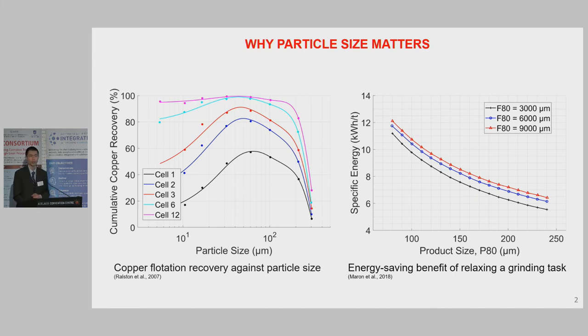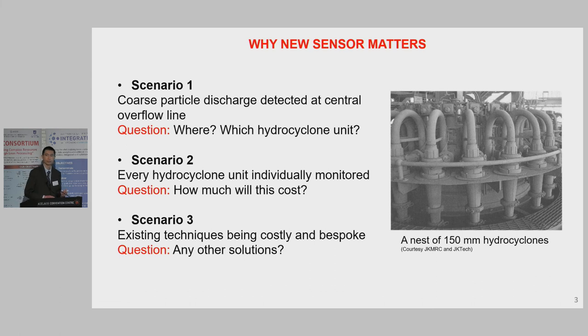Now, how do we tell whether we are grinding to the right particle size? Then we need to monitor particle size. Traditionally, size analysis is done offline, which can introduce hours of delay. For optimal control of the grinding circuit, real-time feedback of particle size information is necessary. Now suppose you've got something that can do online measurement of particle size at the central overflow line where the overflow of individual hydrocyclones merge together. And one day it reports a sudden increase of coarse particles. Then the questions are, where does the problem come from? Is it from the grinding device or from hydrocyclones? If from hydrocyclones, then which unit is malfunctioning?